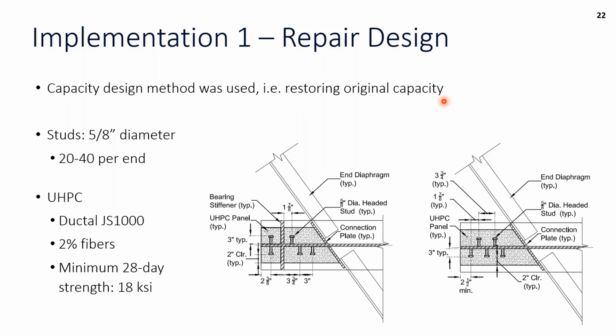For the UHPC, the Ductal JS1000 mix was used with 2% fibers, and this is something that was unique to the specification. They required a 28-day strength of 18 KSI. All of our research was done achieving higher strengths. We did do some tests to show that the 18 KSI was more than sufficient to get the performance that we required. But this really came in that they just wanted to make sure that they weren't rejecting material, because you could see the complexity with some of these beam end designs, and working with a material like UHPC, it's not exactly easy to get rid of if something isn't working properly.